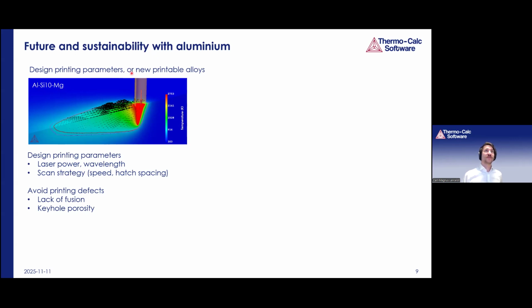So we can design the printer parameters or design new printable alloys, for example, using the modeled melt pool behavior as a function of different laser power, wavelength, also laser beam shape and beam radius, different scan strategies such as scan speed and hatch spacing and hatch rotation and all that. And we can model all of this and optimize the printing parameters to avoid printing defects such as lack of fusion and keyhole porosity.